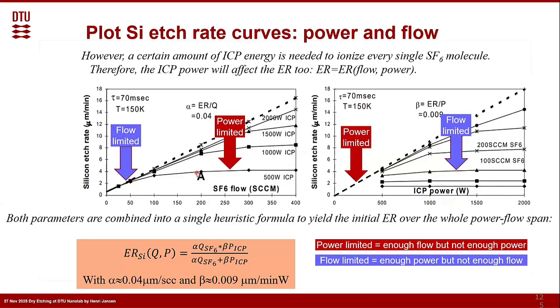We can do the same by making exactly the same plot, where we look at the silicon etch rate, but now we increase the ICP power for a fixed flow of SF6. We see more or less the same curve as here. In the beginning you don't see it, because we didn't measure it here: at an ICP power of 0 there's no plasma.